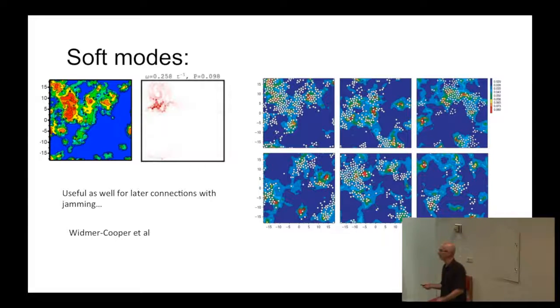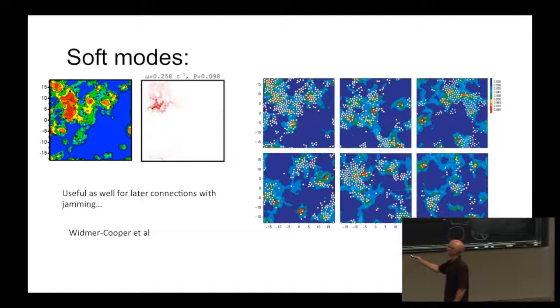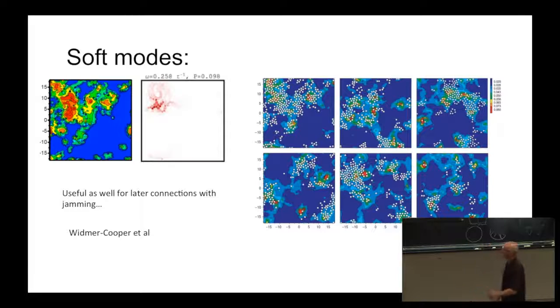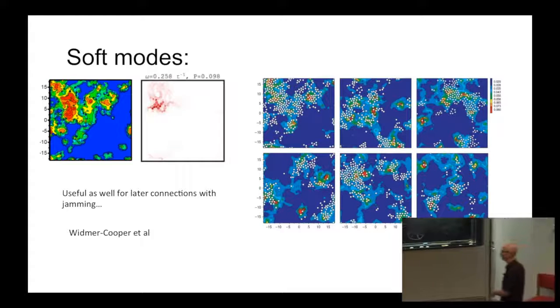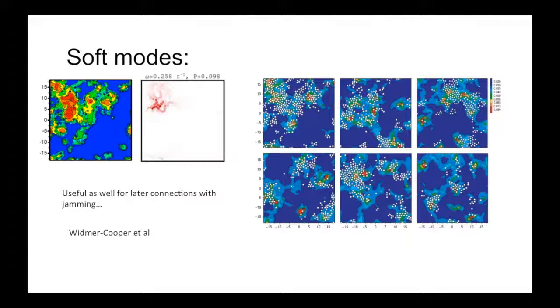And those are generally what we call the soft modes of the system. They basically extend over some length scale, and they do have a length scale associated with them, but they're neither plane wave nor totally localized. Okay? There's some hybrid of a plane wave and a localized mode. And actually, if you look at propensity maps in the system, in some systems, this is probably not true in all, and it's worth going back and looking at this.